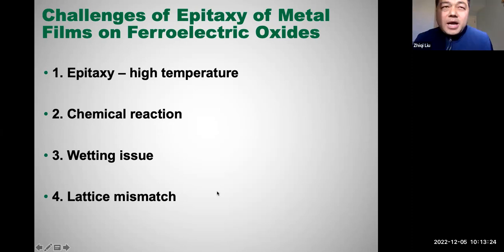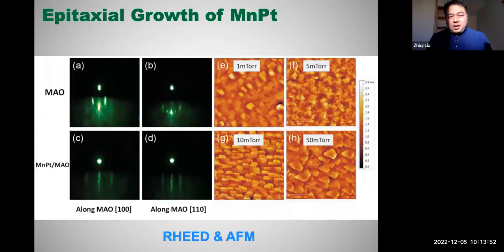The other thing is the lattice mismatch. Most of metals have a lattice constant around 3 angstrom, but for our oxides, especially for our perovskite single crystal substrates, they have lattice constants around 4 angstroms. So all these factors could lead to the unsuccessful epitaxy of metals on oxides. But we can always try to find a suitable substrate for a certain magnetic metal.